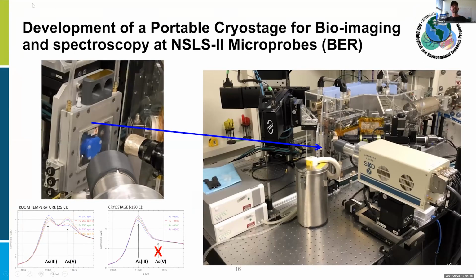And some other work on in situ environments that our community tends to, the really low temperature geochemistry, maybe is more of the biogeochemistry side, where we might want to do imaging of some really delicate samples or samples that have redox sensitive elements like arsenic. You know, in this example, we're actually measuring a fern that had arsenic in it. And you can see in the bottom left corner, when we do that at room temperature, we induce the chemistry that we're measuring. But if we do that at cryogenic temperatures, we can actually capture it before it transitions to the arsenic 5.